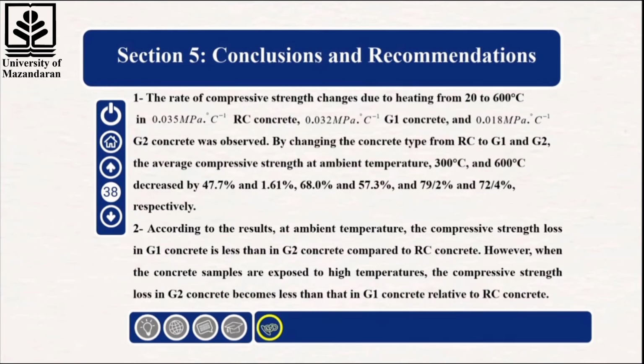Section 5. Conclusions and Recommendations. 1. The rate of compressive strength reduction due to heating from 20 degrees Celsius to 600 degrees Celsius was calculated as 0.035 megapascal per degree Celsius for RC concrete, 0.032 for G1, and 0.018 for G2. When the concrete type was changed from RC to G1 and G2, the average compressive strength at ambient temperature, 300 degrees Celsius and 600 degrees Celsius, decreased by 47.7% and 61.1%, 68% and 57.3%, and 79.2% and 72.4%, respectively.